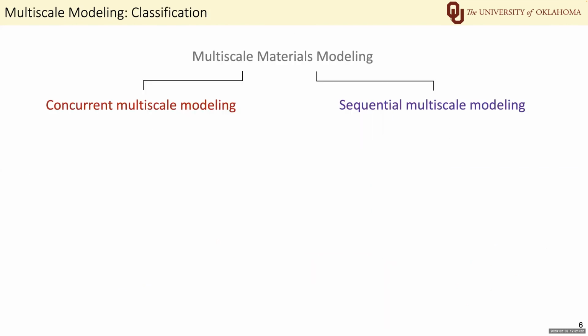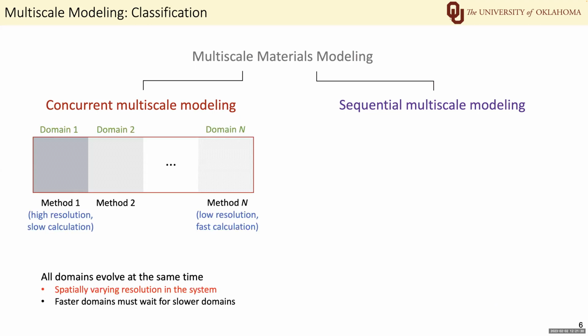So there are two types of multi-scale modeling: concurrent modeling and sequential modeling. The concurrent multi-scale modeling is preferred for systems with spatially varying resolution. It partitions the system into 2 or more domains. In each domain, we use a different method. Some methods have higher resolution and the calculations are slower. Other methods have lower resolution and the calculations are faster. Since all the domains are in the same system, they must evolve at the same time. This means that the faster domain must wait for a slower domain.